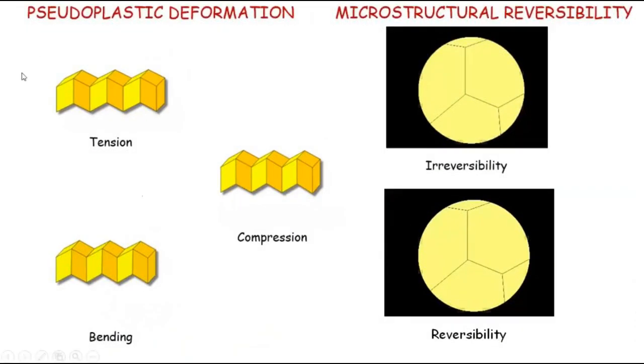Let's hope. And we have these two things, and with a couple of animations, we'll try to explain what the pseudoplastic deformation is. In this case, we are considering two variants of martensite, two orientation variants. So one is colored yellow and the other orange, and for the purpose of this slide, yellow is favored by tension. Now it's a shear. So tension favors one orientation and compression would favor the other. In this case, tension will favor the yellow and compression will favor the orange.